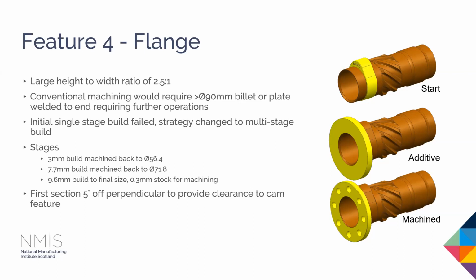The challenge with this part was mostly down to the fact that it's such a tall feature compared to its width. It's 20mm tall and only 8mm wide. So that meant there was quite a long build-up. We also had to tilt the part a little bit because the part had built so high that we needed a bit of clearance so we didn't crash into it with the deposition head.